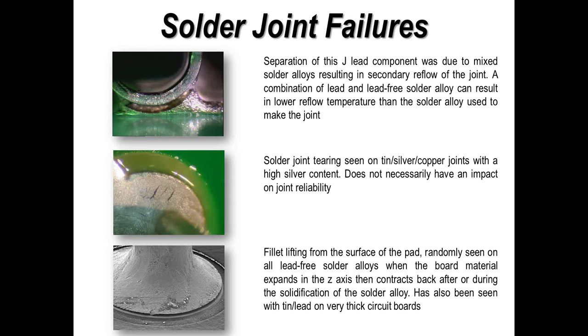In the bottom example, this SEM is fillet lifting, which can happen after selective wave soldering or intrusive reflow. And again, the solder has cooled, the board is still contracting back and leaving the solder slightly lifted from the surface. Again, there is criteria within IPC 610 for this on lead-free joints, not on tin lead, but on lead-free joints.